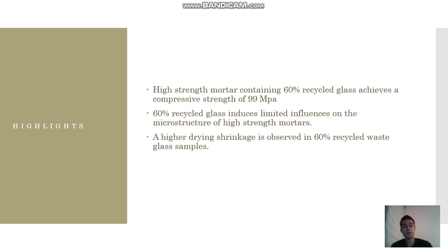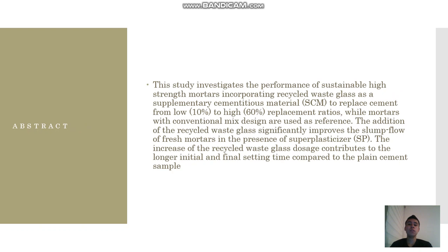Abstract: This study investigates the performance of sustainable high strength mortars incorporating recycled waste glass as a supplementary cementitious material to replace cement from low 10% to high 60% replacement ratios, while mortar with a normal mix design is used as reference. The addition of recycled waste glass significantly improves the slump flow of the fresh mortar in the presence of superplasticizer. The increment of recycled glass contributes to longer initial and final setting times compared to the plain cement sample.